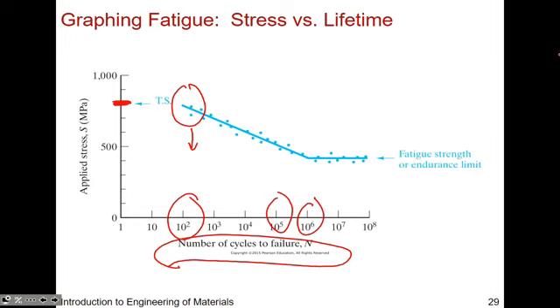There's a limit below which you can safely say the material will probably not fail or will have a much longer cycle life to failure, and that's the fatigue strength or endurance limit. So if you operate below this threshold for this particular material with a tensile strength of this value, most likely it will not fail in your lifetime or in the number of cycles that you can track. That's extremely generous and